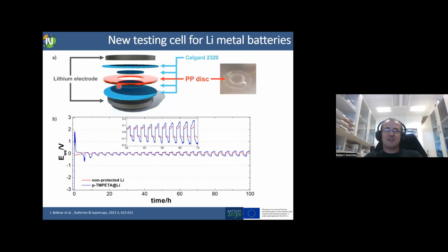So that's what we designed at the beginning. We used a polypropylene disc, which was pressed on the separator. Now in the new modification of the cell, it is enough that we press the edge of the separator with a special tool, and that creates a non-permeable area for lithium ions, and that also prevents extensive electrochemistry on the edges. And now the situation is different. Now you can see we have higher polarization, as we expected from the beginning, but this polarization is increasing more in the area with the electrode with TMPETA compared to the electrode which was not covered.